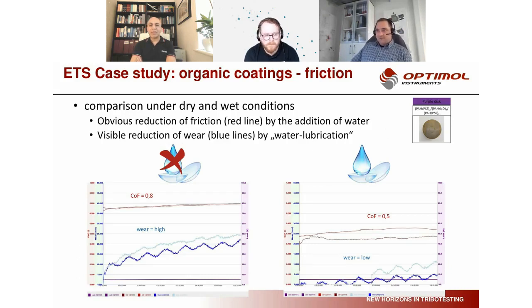with online measurement, you see that the COF under wet conditions is nicely low. In this application, the wear is represented in the blue curves, and the friction is represented in red. And you also see that the repeatability is quite nice, even if this is an exotic application, while under dry condition, obviously, friction is higher and wear is higher. And this is how you can easily rank different coatings, different materials, different lubricants in terms of wear resistance and friction behavior in a model test.